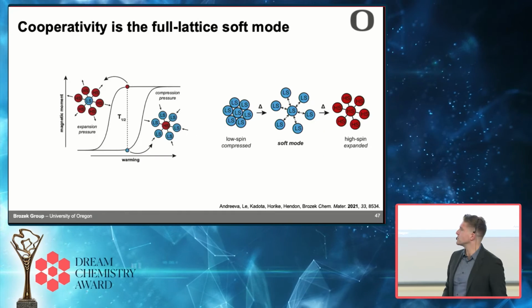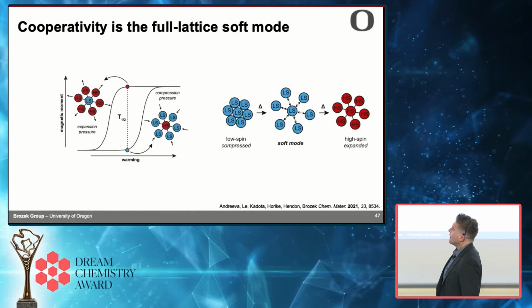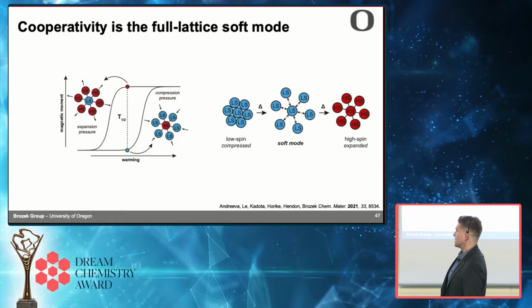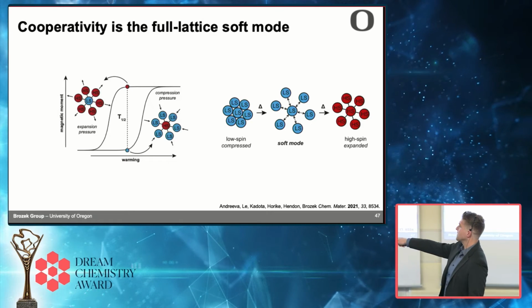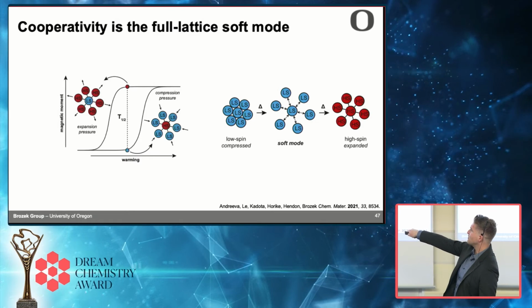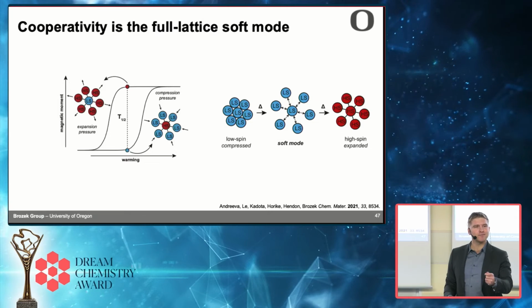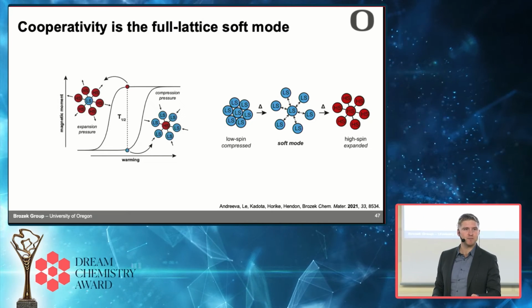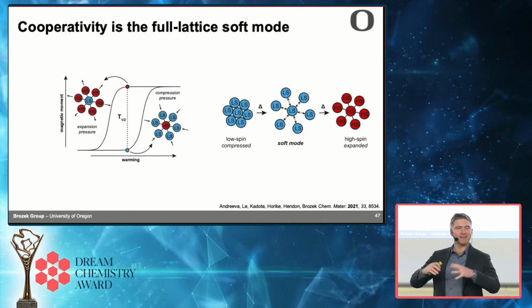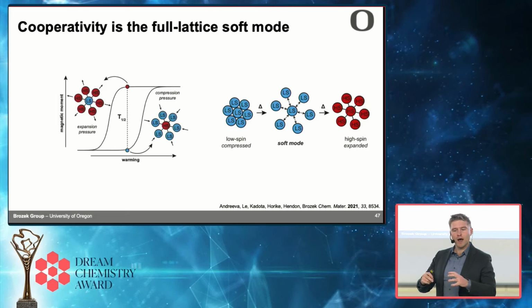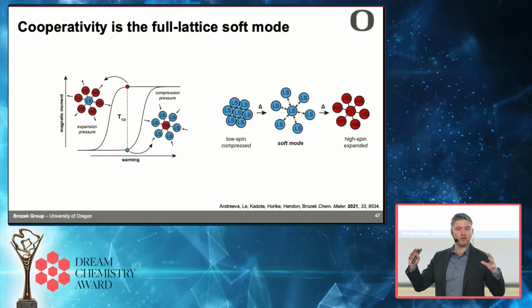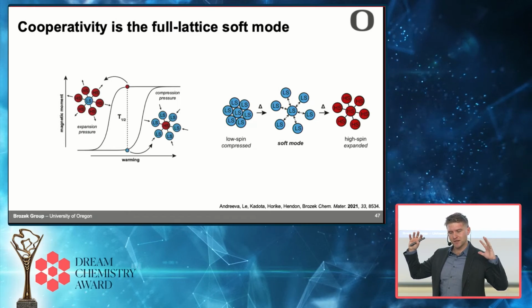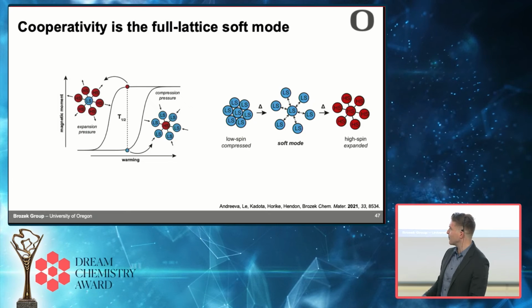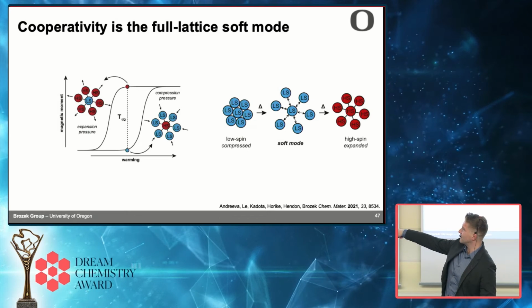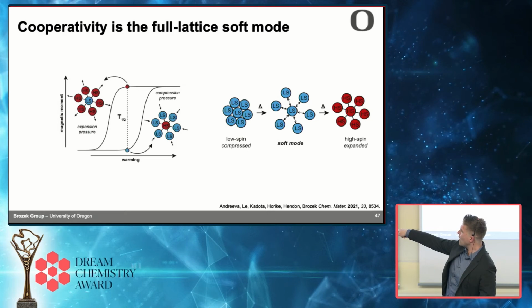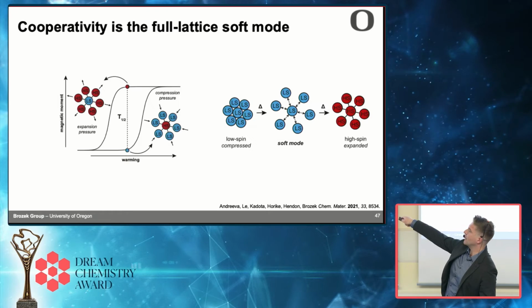And so this is my proposal. Spin crossover happens here. The hysteresis arises from when you try to heat up your material, a metal site, an iron site, tries to go high spin. Everything around it is low spin. When it tries to go high spin, it really puts a lot of pressure on the crystal, and all the surrounding neighbors say no, and they push it back into low spin. So this is why you heat it, and it stays low spin, low spin, low spin, and then all of a sudden, it flips into high spin.